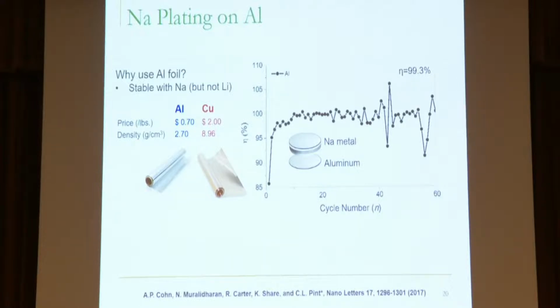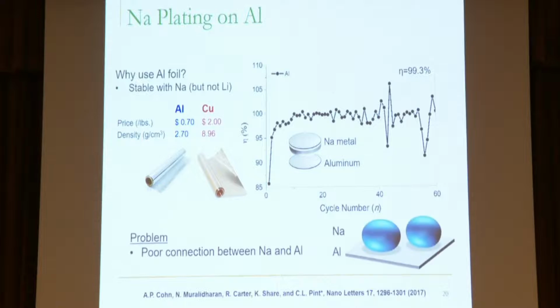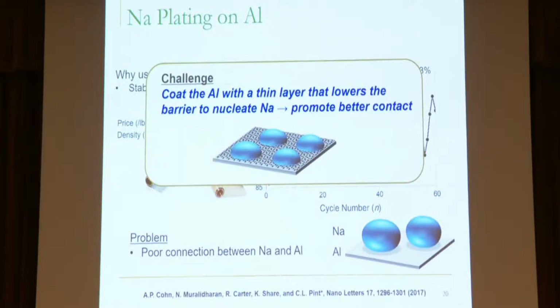And this comes from the difficulty that, well, we're actually plating metal onto a surface. The surface really matters. Aluminum didn't seem to be that good. Some of these deposits that we made were very big, and they would literally just sort of crack off. And we saw that. So we had to go in and engineer the interface of these materials so that we could get good adhesion of these layers and get better performance.